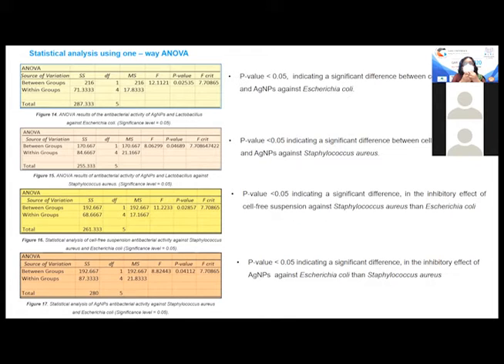That is also indicating a significant difference between cell-free suspension and silver nanoparticles against Staphylococcus aureus. Another p-value less than 0.05 indicates a significant difference in the inhibition of cell-free suspension against S. aureus than E. coli. And the last figure shows you the p-value less than 0.05, indicating a significant difference in the inhibition of silver nanoparticles against E. coli than S. aureus.